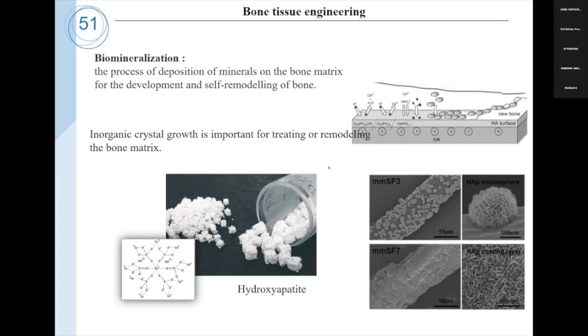If we use SBF solution, simulated body fluid, with ion concentration nearly equal to those in blood plasma, it could reproduce the formation of apatite on bioactive ceramics in vivo. So as apatite particulates are generated on synthetic materials, new bone may form on this mineralized layer. And implants may be stabilized by increasing the material-bone interface strength. Without biominerals, it is very difficult to interact with the host tissue. If a scaffold has biomineralizing capacity, it easily bonds to the native tissue once we implant it at the particular targeted site.